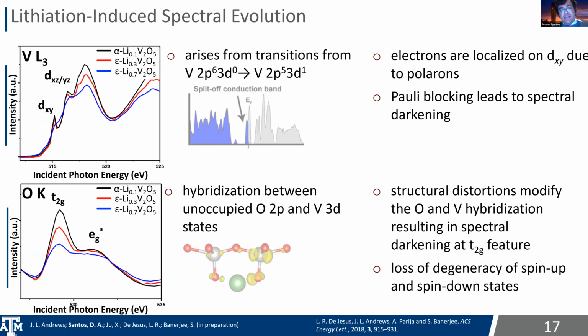One using the DXY feature of the vanadium L3 edge, and then the relative intensities of the t2g and eg features at the oxygen K edge. And what we do in a scanning transmission X-ray microscopy experiment is we take a finely focused X-ray beam, and we can, with spatial resolution of 25 nanometers or even better, start to resolve differently lithiated domains within individual particles and across ensembles of particles.